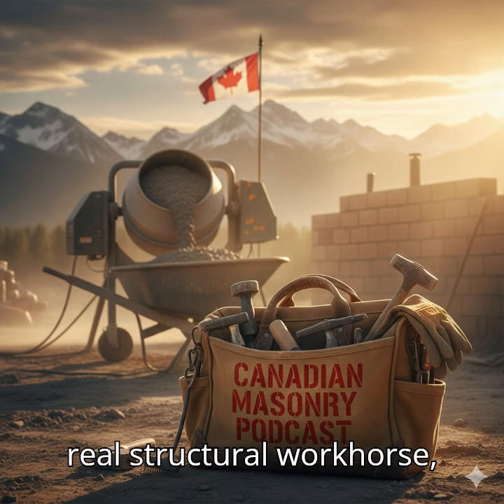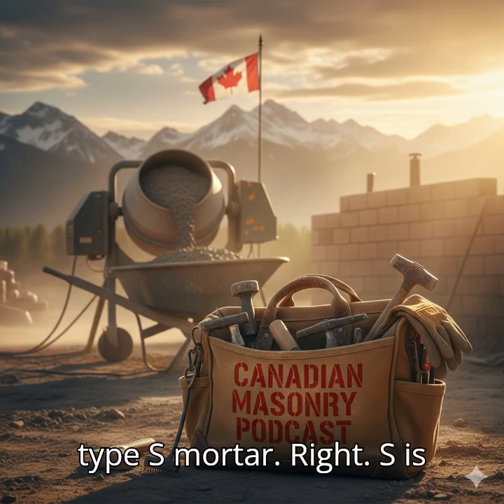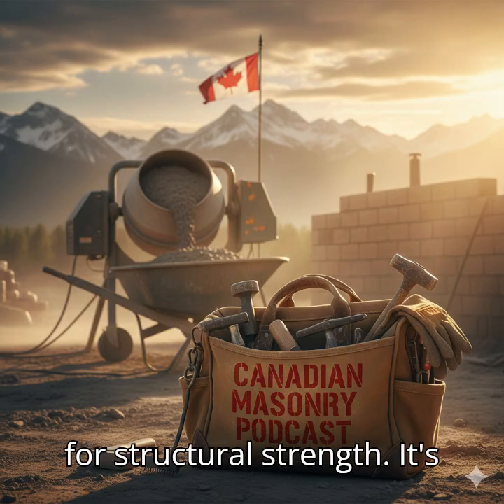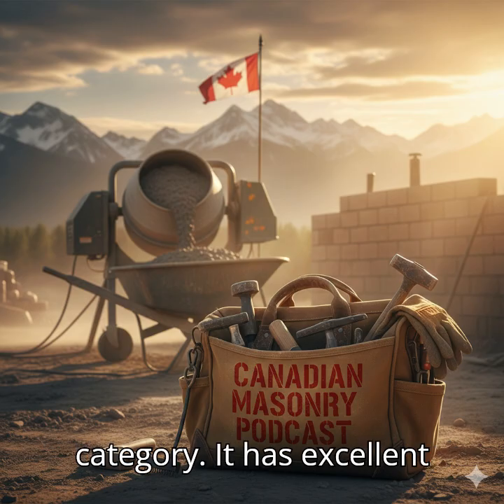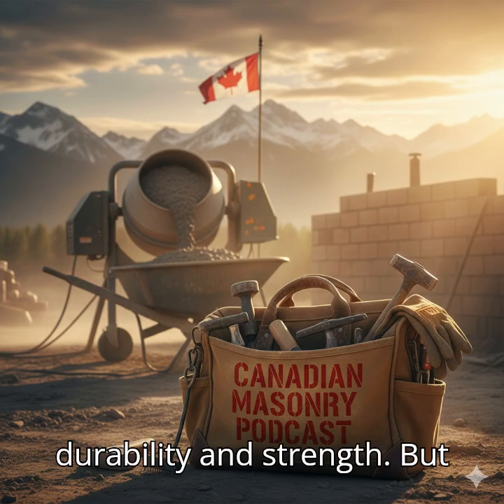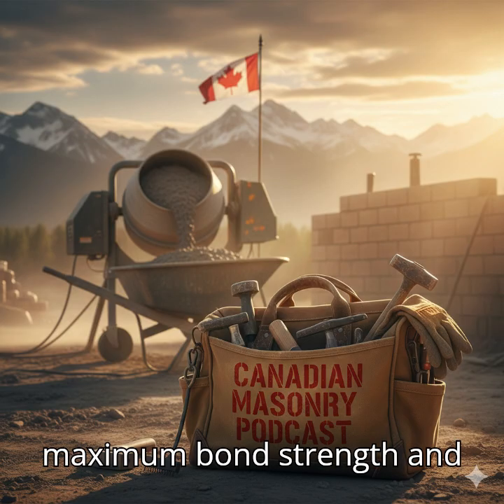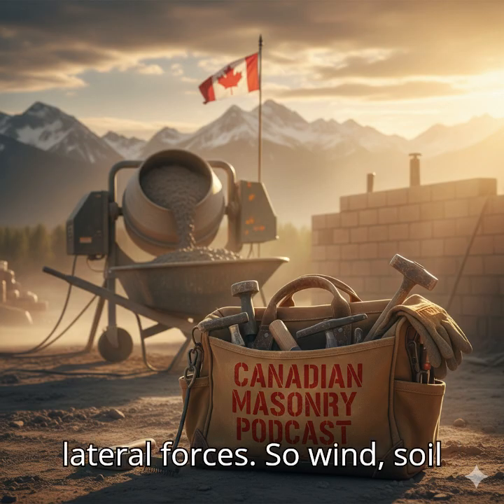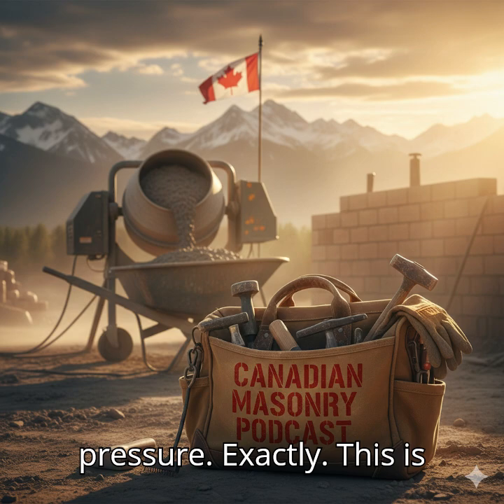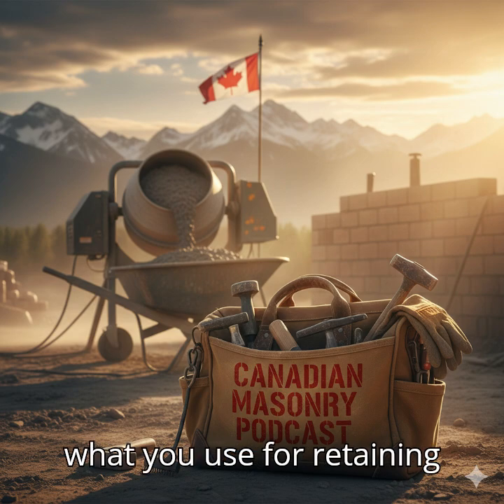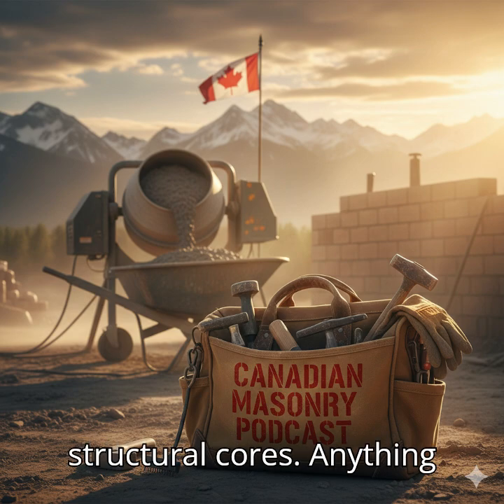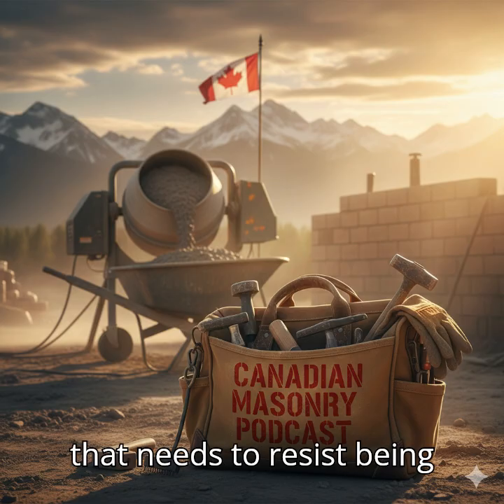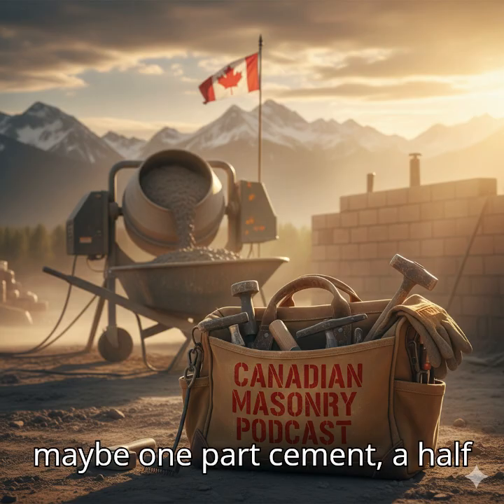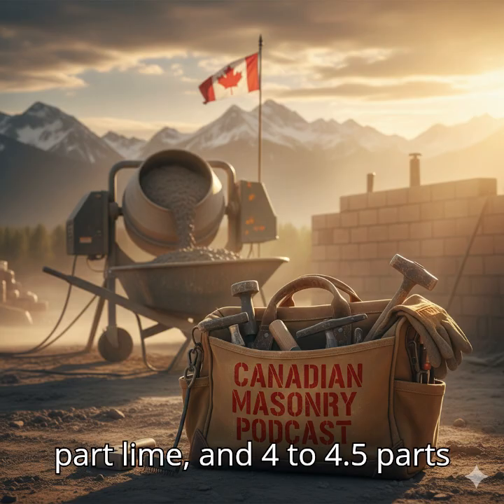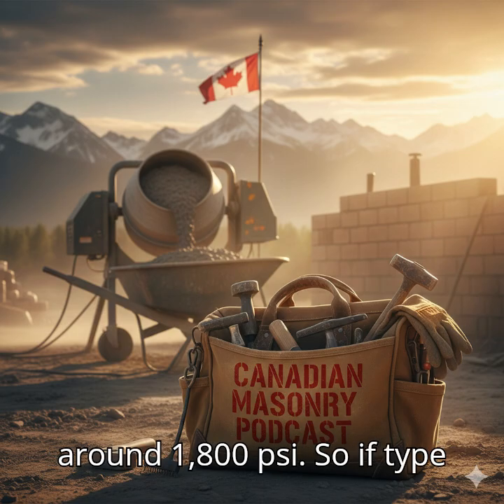Okay, next up is the real structural workhorse, Type S mortar. Right. S is for structural strength. It's in that medium-high strength category. It has excellent durability and strength, but its real claim to fame is its maximum bond strength and fantastic resistance to lateral forces. So wind, soil pressure. Exactly. This is what you use for retaining walls, reinforced masonry, structural cores, anything that needs to resist being pushed sideways. A typical mix has a bit more lime, maybe 1 part cement, 1/2 part lime, and 4 to 4.5 parts sand. The strength is usually around 1800 psi.